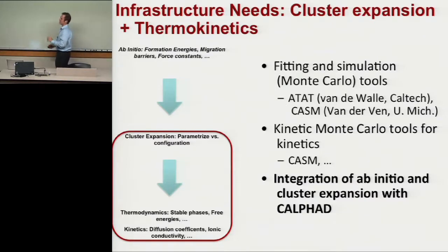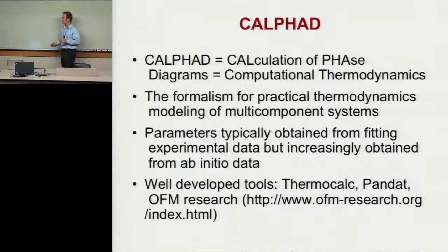And you want to integrate that with standard thermodynamic modeling of alloys, which some people call computational thermodynamics. I refer to it as the CALPHAD method. Very quick introduction to that. It is basically the formalism that you use for calculating phase diagrams. Every time you look up a phase diagram, it is almost always calculated with this method. It's essentially an elaborate fitting scheme for parameterizing free energy functions to calculate phase stability. It's also the foundation for calculating kinetic behavior, because you need the thermodynamic driving forces for any kind of kinetic modeling. These tools are well developed and exist.